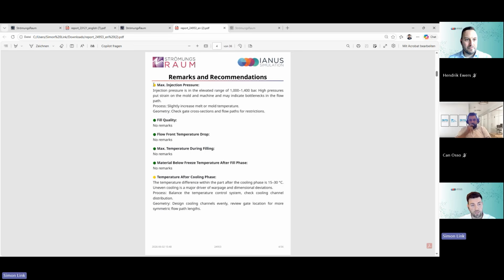Then we have the yellow color. So where we look at this injection pressure, for example, and in this case, it says we have an injection pressure between 1000 and 1400 bar, and this is a very high pressure, and this could lead to an issue. And you should probably have a closer look at it. And this makes it very easy for the user to look at the different measurements and say, okay, this looks fine. I will have a closer look at the injection pressure.